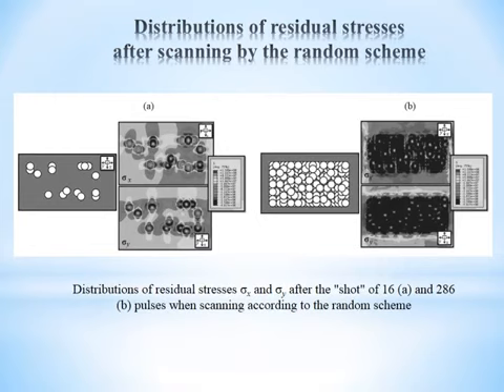The obtained numerical results show that the method of choosing the scanning direction has a strong influence on the anisotropy of residual stresses. In particular, it was found that with a zigzag scanning scheme, CRS in the scanning direction is much greater than in the perpendicular direction. Therefore, the choice of the scanning direction is an important separate task that should be solved before using LSP to optimize the residual stress fields.